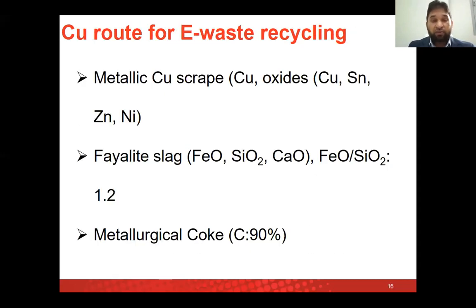So metallic copper scrap that contains copper and the oxides of copper, tin, zinc, and nickel. That comes as a metallic copper scrap. This is a composition. Of course, the majority of that is the copper metal itself, not oxides. The exact composition you can find in our paper.